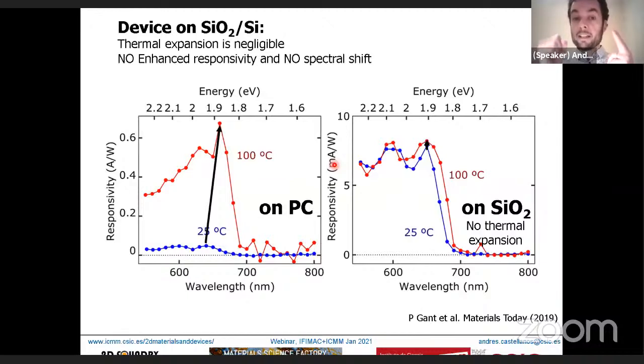Silicon oxide has a negligible thermal expansion. So in these kind of devices, you only have the effect of temperature, not the effect of biaxial strain. We fabricate this set of devices and subject them to the same temperature cycling.